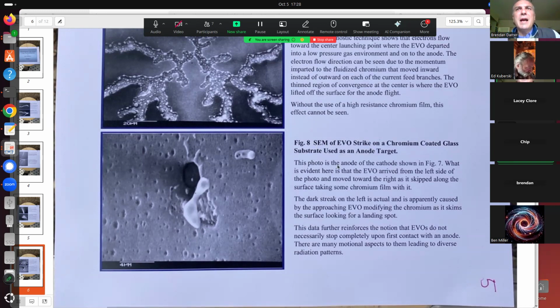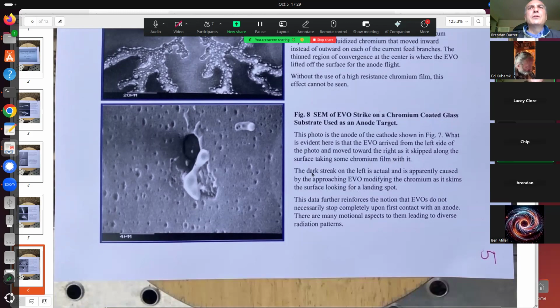This photo is the anode of the cathode shown in figure 7. What is evident here is that the EVO arrived from the left side of the photo and moved toward the right as it skipped along the surface, taking some chromium film with it. The dark streak on the left is actual and apparently caused by the approaching EVO modifying the chromium as it skims the surface looking for a landing spot.